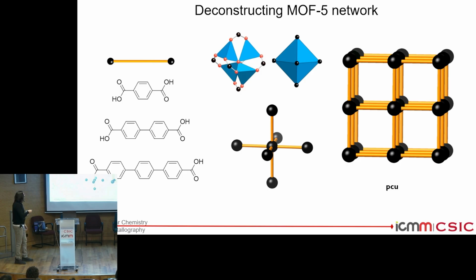Okay, so if we look at the MOF-5 structure and the building blocks that I was showing in the previous slides, you see that we have this type of cluster that has 6 points of connection, 6 points of extension, disposed in an octahedral shape. The linker is linear, but as we know already, also from Robson's work, it doesn't matter how long the linker is, as long as you keep the same degree of connectivity. All right, so if you have the MOF-5 components, you will basically always have a primitive cubic PCU type of network, regardless of whether you have a linker with 1, 2, 3, 4 benzene rings, as long as the connectivity is always the same. So this is the theory, but we have to jump a little bit again.